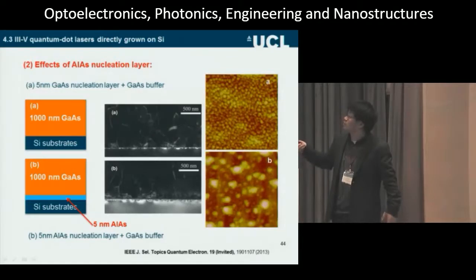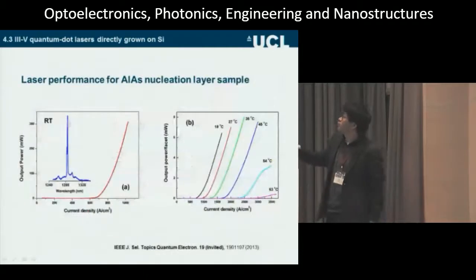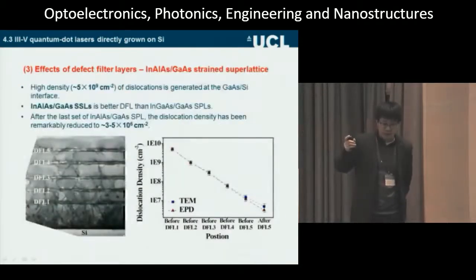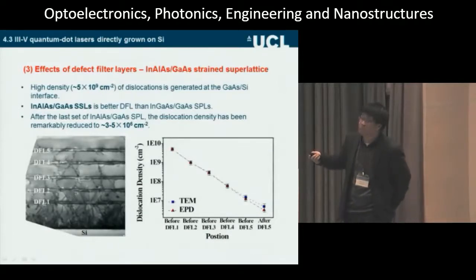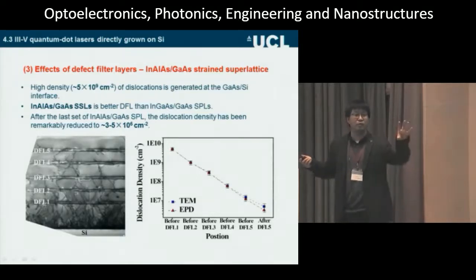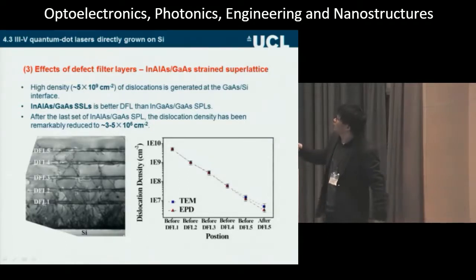The next trick is how to use another approach to make the nucleation layer better. We use AlAs nucleation layers, which confine a lot of defects at the interface. After that, we do get a good laser at 1.3 micron, and we push the laser operation up to 63 degrees. The other thing is, you do have a lot of defects, so you need to study the dislocation filter layers to filter all the dislocations. This one is not a particularly good sample, but it's easy for TEM to study the number of defects. You can see when you start, you have 5×10^9. After each dislocation filter layer, the dislocation density is reduced. Finally, we get a number around 3 to 5×10^6 per centimeter squared.